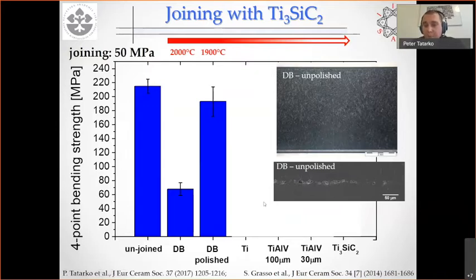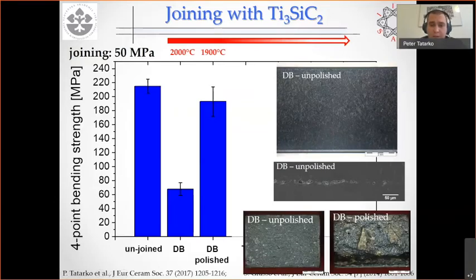In case of the polished sample, we could not even find the interface. So that's why I'm not showing it here. But what I can show is the fracture surfaces after the test. Here you can see the unpolished fracture surface. So you can see it's very smooth. Basically, it just delaminated where the initial joint was. In case of the polished surface, however, you can see we got a really standard, typical fracture surface of silicon carbide, which suggests that the joint was very strong, and we almost reached the initial strength of the reference material.